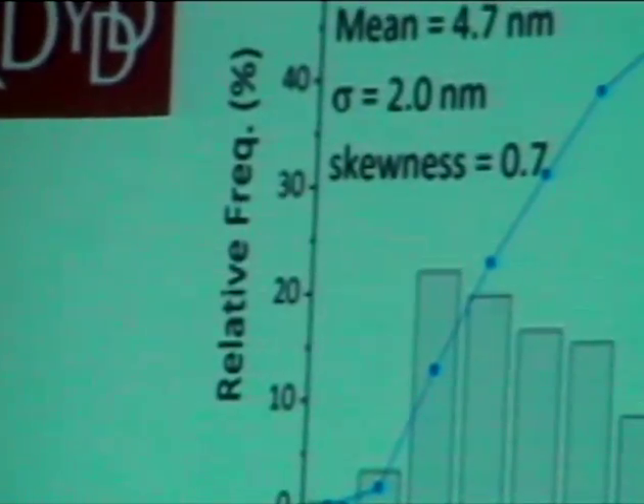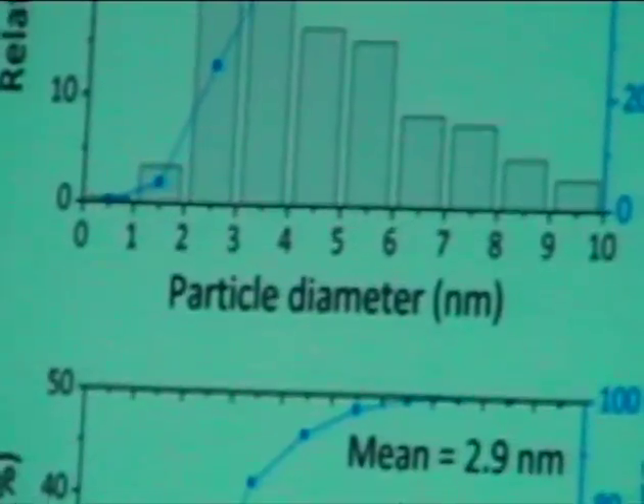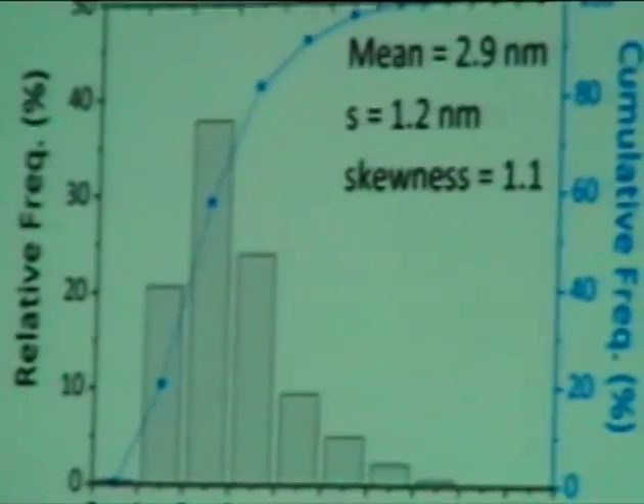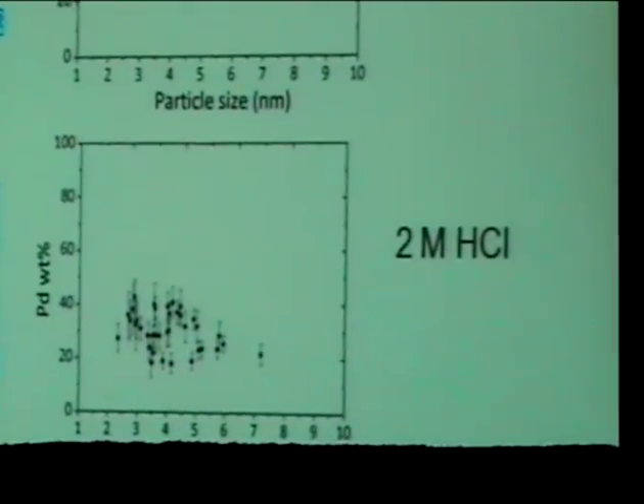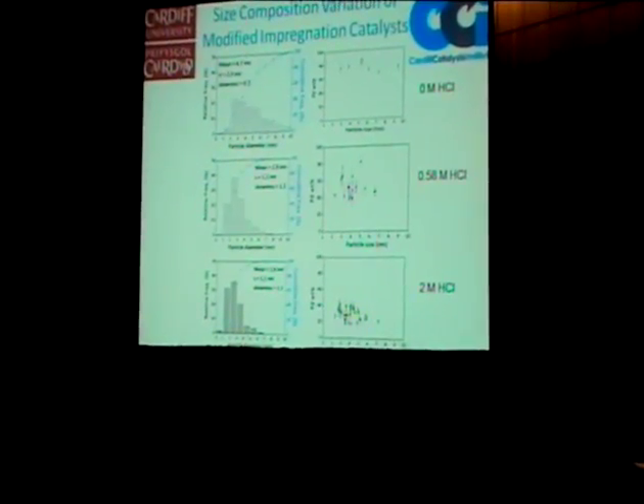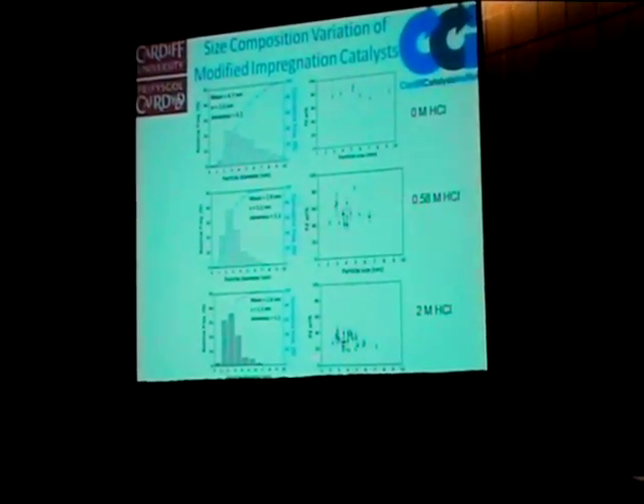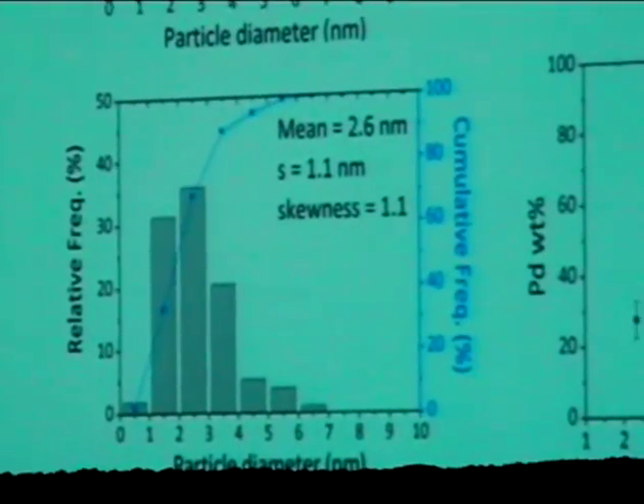So looking at particle size distributions and the particle composition distributions as a function of the concentration of chloride that we use in this preparation, we can see that when we follow this preparation without any HCl, we still get a wide particle size distribution. However, the composition distribution is now pretty much uniform, with around 80% palladium in all the particles. As we increase the HCl concentration, we tighten up the particle size distribution to a mean particle size of around 3 nanometers. And we also change the composition of the catalyst. As we go to stronger HCl concentrations, we see a similar particle size distribution, and now we see very gold-rich particles. So this preparation method allows us to tighten up the particle size, and the concentration of HCl also allows us some control of the composition of the nanoparticles in the catalyst.